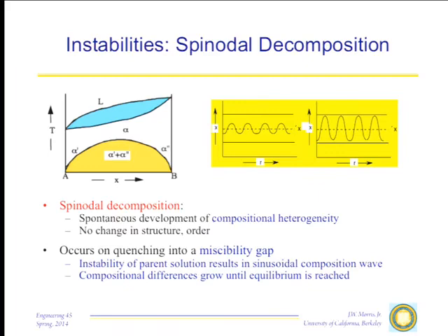Once the composition reached a certain value, one of the two ends of this phase became ferromagnetic. So he wound up with ferromagnetic, paramagnetic, ferromagnetic, paramagnetic, and made a hell of a good magnet that's still used today for many applications. So lots of applications of this kind of procedure, and often they do involve accomplishing a transformation through a cascade of instabilities to get the right kind of distribution of your final product. Very difficult to think of another way to make a material that has regularly spaced discrete islands of ferromagnetic phase, but this does it automatically.